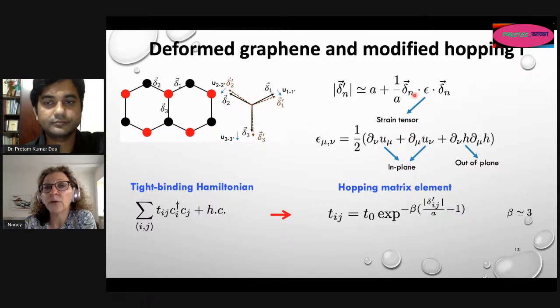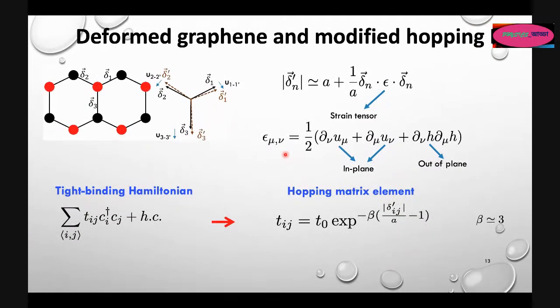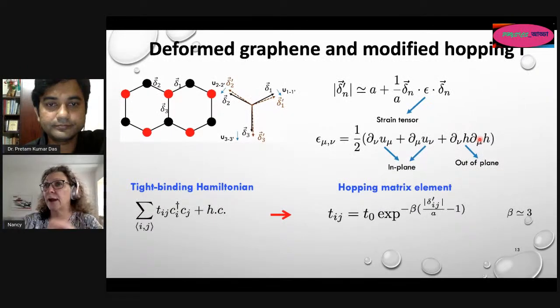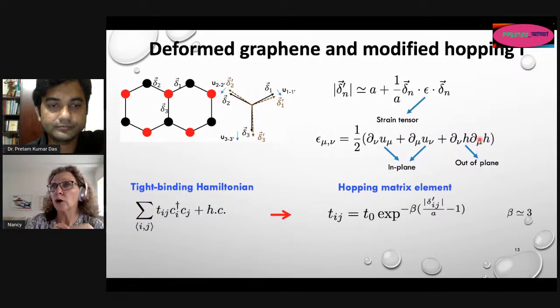So in elasticity theory, we describe the changes in these positions with a quantity that is a tensor with two indices, known as a strain tensor, and it is described in this case by how the in-plane positions of the atom change, and that's why it's a derivative. So it's the change in the in-plane positions plus a term that is a change in the out-of-plane positions. That is, if the material is a membrane, the atoms could be moved in the plane where they are located, which is what happens when you apply a tensile strain or a compressive strain, where the material stays in a flat surface, or the atoms can be moved in a third dimension, right?